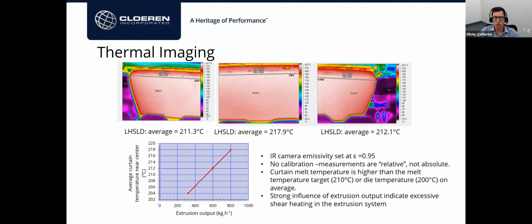This was also confirmed with thermal imaging, but the cool part of thermal imaging is that you can also look at that response as a function of extrusion output, and you can see here there's almost a linear temperature increase as the extrusion output is increased. So it really shows that there's quite a bit of shear heating in the system, which is not unusual for these high viscosity polymers.